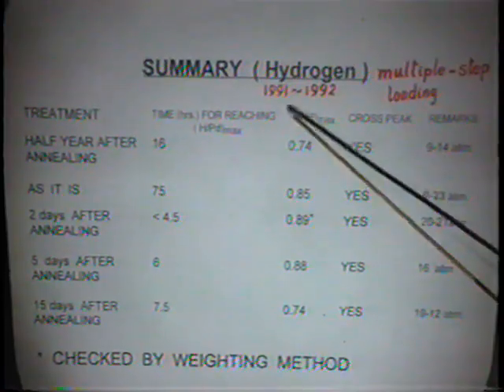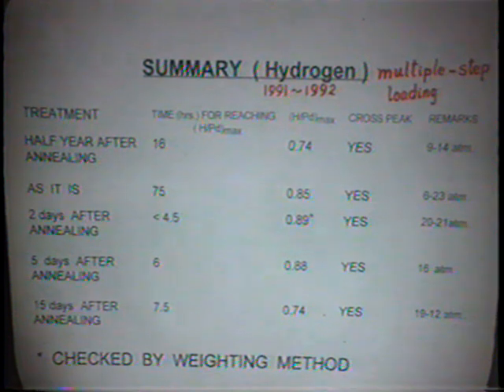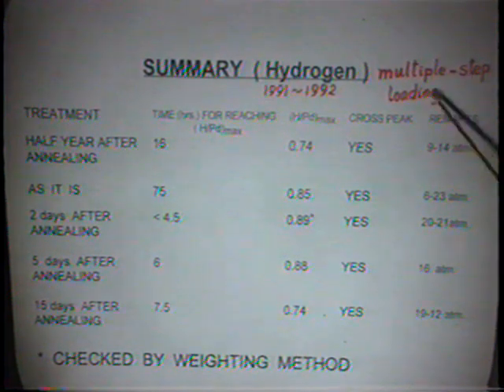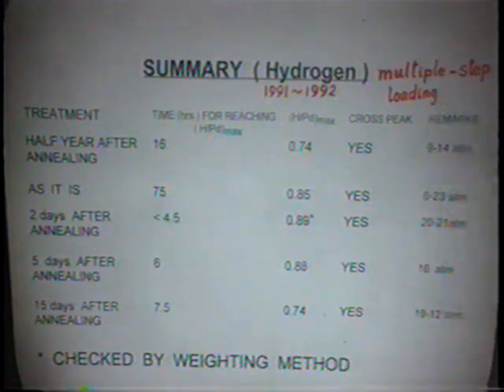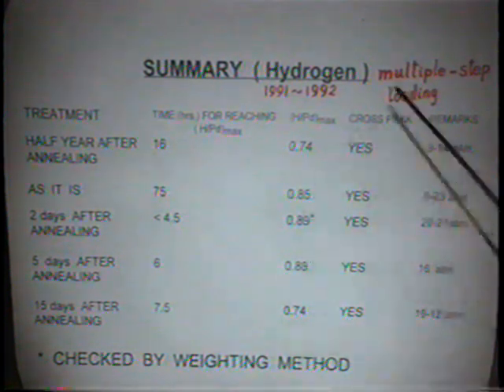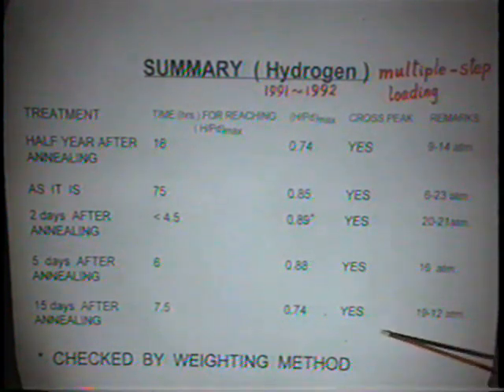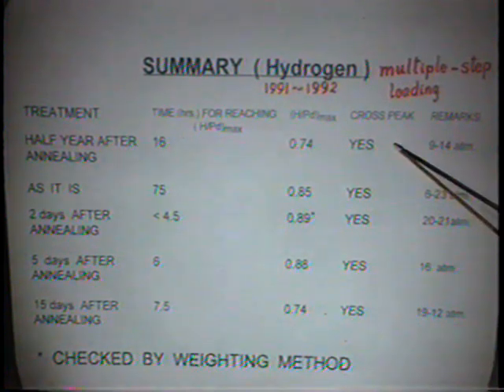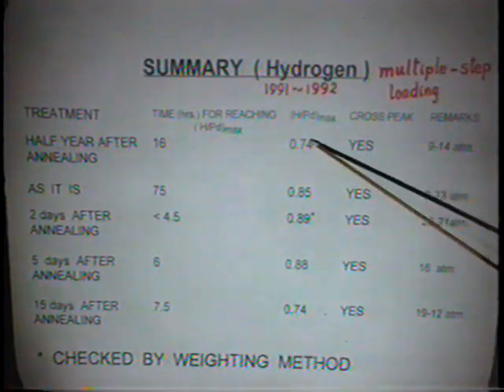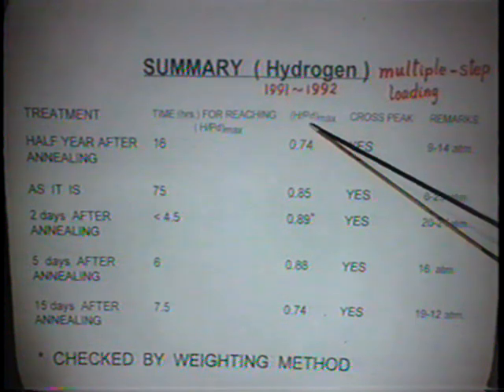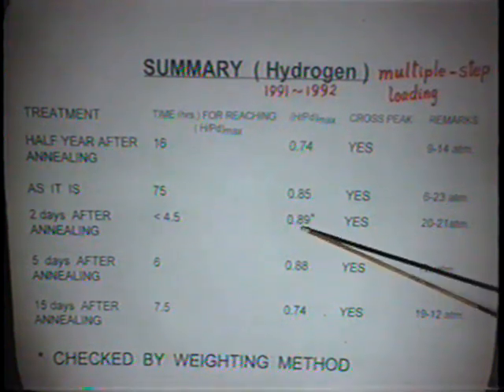This is a summary of the first student's work. He is using hydrogen in 1991 to 1992. We just use the multiple step loading. We put the gas in and degas, and put the gas in, degas. Using this method, we can cross the peak. And we reached the loading ratio, the maximum is 0.89.